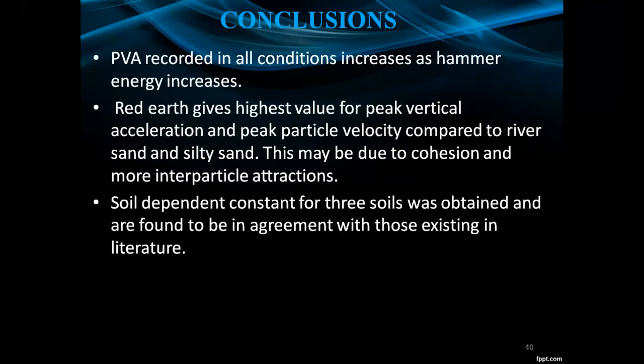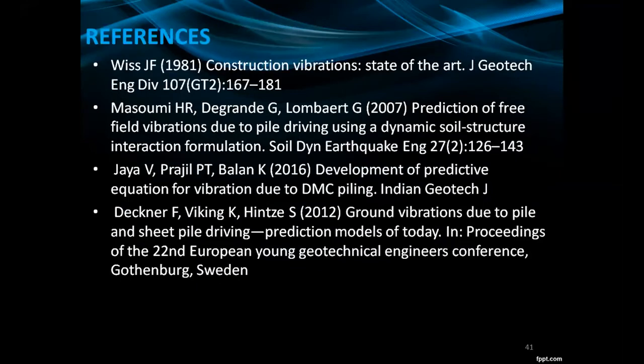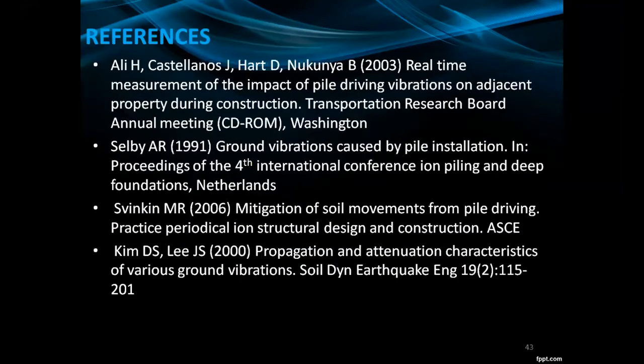Peak vertical acceleration recorded in all conditions increases as hammer energy increases. Red earth gives the highest value for peak vertical acceleration and peak particle velocity compared to river sand and silty sand. This may be due to cohesion and more interparticle attractions. Soil-dependent constants for the three soils were obtained and are found to be in agreement with those existing in literature. And these are my references.